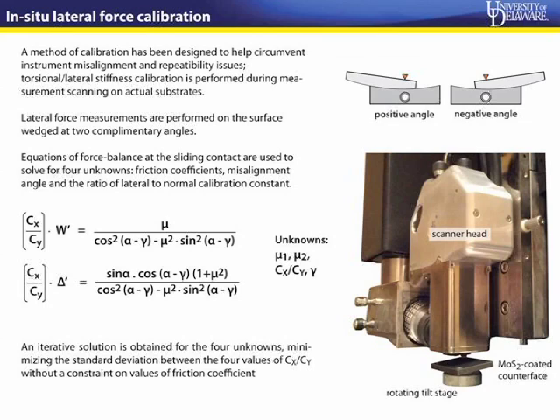Of course, ideally, mu1 and mu2 should be equal because you're not changing the substrate, you're only changing the angle. But we do not impose that constraint on mu1, mu2. So again, you end up with four equations and four unknowns. We solve these equations iteratively to get a solution, minimizing the standard deviation between Cx, Cy to get a solution for Cx, Cy, mu, and gamma.